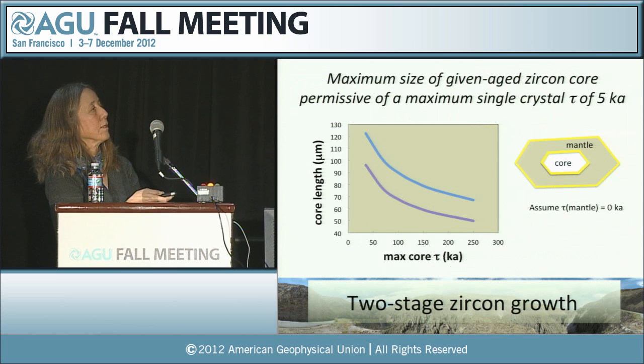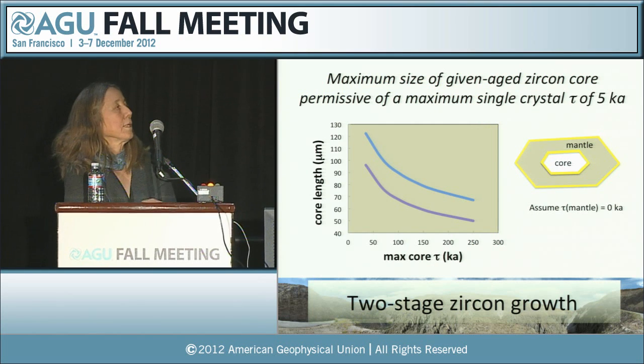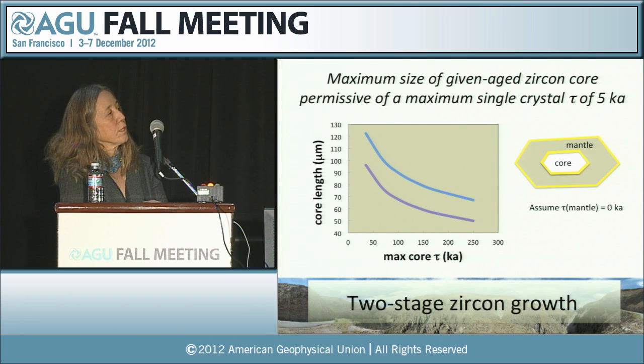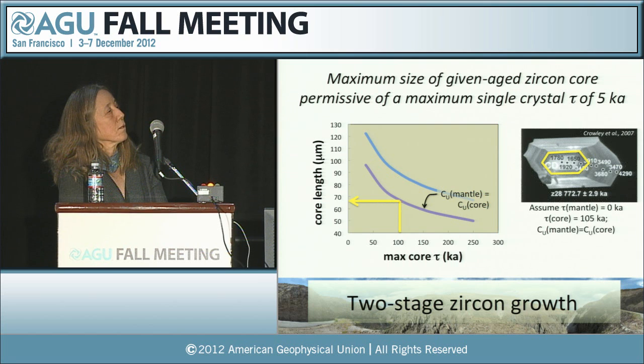So this is what I started to tell you about. I've looked at what the length of the core could be, assuming some maximum core tau. So if I assume that the mantling region is 0 years, and I assume that the core is, for example, what I determined, this 105,000 years, we could estimate then something about the interior domain, this interior core, and how big it could be. A core of 105,000 years could be this big and still preserve a single crystal age of 5,000 years.